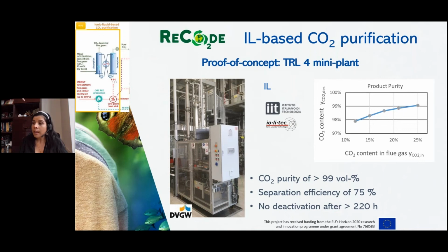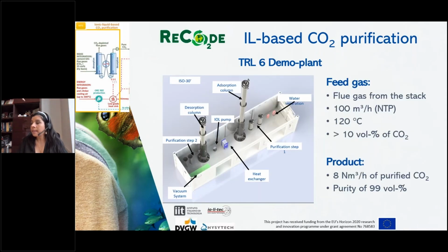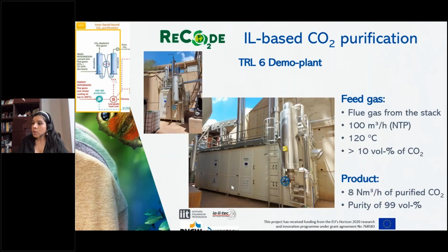And this was all done thanks to the development of a new kind of ionic liquids that are being utilized in our demonstration plant and that are right now treating 100 cubic meters per hour of flue gas that arrives at the plant at a temperature of 120 degrees Celsius, and that contains concentrations as low as 10% in volume of CO2. The final goal is to produce 8 cubic meters per hour of purified CO2 with a purity of 99%. And here you see some pictures of the plant that is already installed at Titan facilities.